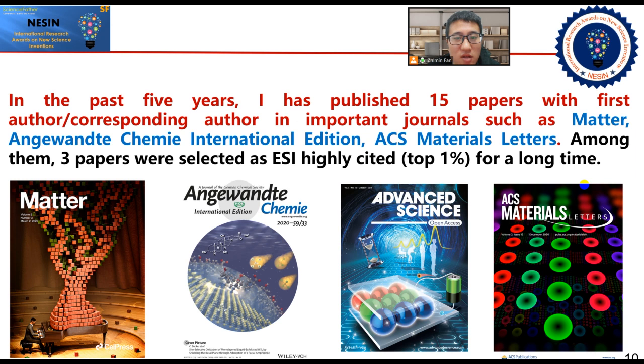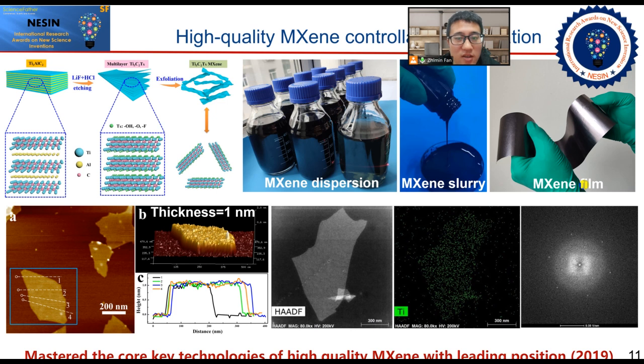Therefore, in the past 5 years, I have published several high-level papers on MXene in top international journals in the field of chemical materials, such as Advanced Materials and Advanced Science, and received the attention of academics globally, including Gogotsi, the inventor of MXenes. After years of exploration and research, we have now achieved the preparation of high-quality MXene in batch and small scale, and have made key progress from dispersion to slurry to thin film. Through atomic force microscopy and transmission electron microscopy, we can see that the prepared MXene layers can reach the macro level, and the surface is smooth and neat, without obvious oxidation traces. And this technology is in the leading position in the international arena.